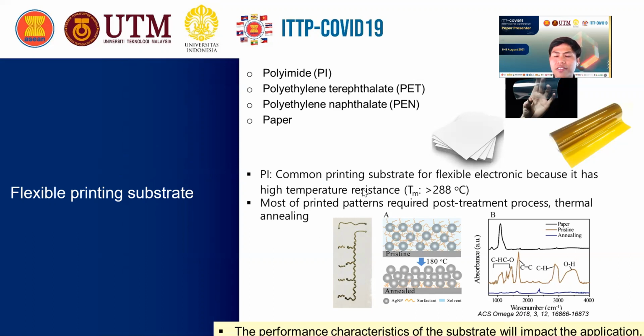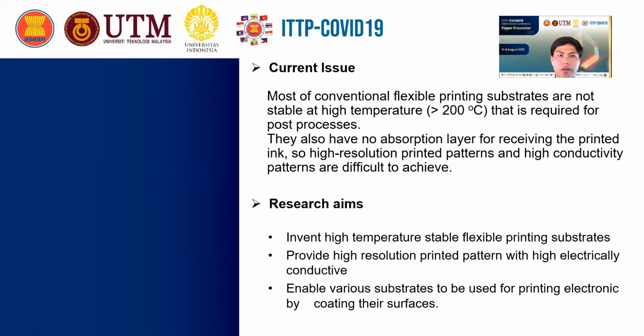And of course, the selection of the printing substrate really impacts the application that you want. As we have experience working on the development of conductive ink, we have successfully made carbon nanotube ink, and we also successfully printed the ink using inkjet printers. But one thing that remains challenging is that finding a perfect substrate for the application is very difficult. Previously, we used a paper printing substrate, and we had difficulty making the printed pattern conductive or making high resolution.